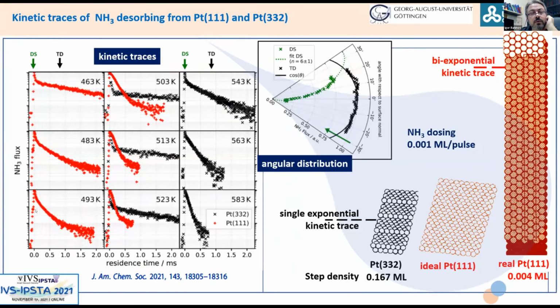And this is what we are seeing in this kinetic trace. First of all, this sharp feature in the beginning is direct scattering of ammonia. So ammonia that hits the surface and bounces back in a single bounce collision. And this produces a very narrow angular distribution at the specular angle with respect to the incident beam, independent of surface temperature, but we are not after that. We are actually after the slow component. The slow part, this long trace, corresponds to desorption. And that's what we see.